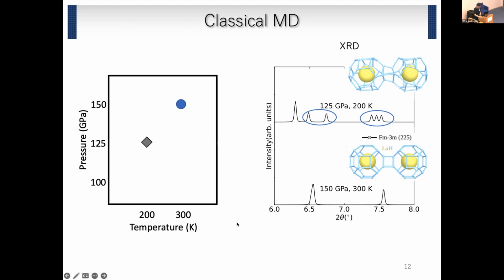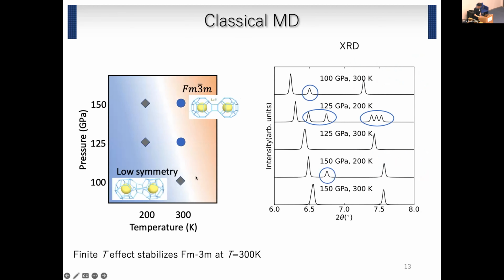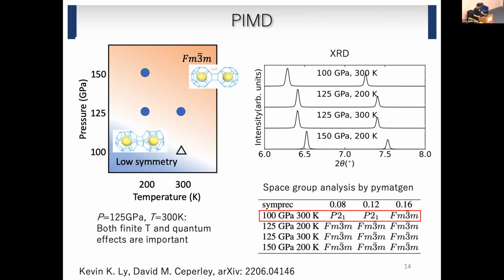And so we performed calculations for these 5 points. We have seen that when the temperature was 300 Kelvin, the structure is symmetric. But for these 3 points, the cage has some distortion. So from classical MD, this result suggests there is some phase boundary here. And at 300 Kelvin, if we apply pressure as high as 125 gigapascal, then the symmetric structure is stable. And then we move on to the PIMD calculation.